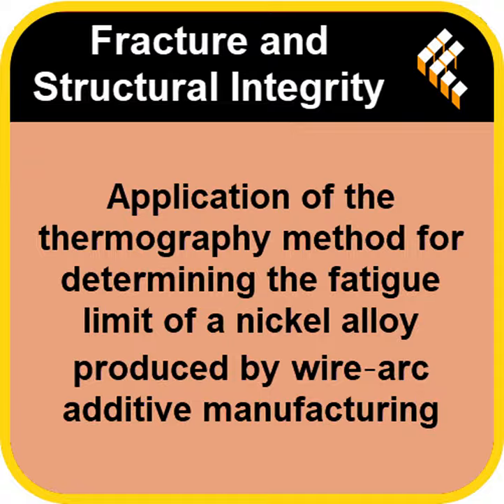So let's get to the bottom line. What does this all mean? We have this rapid, precise answer, 383 MPa. How did that compare to the old, slow, traditional method? Right, this is the validation step, the most important part. They didn't just stop there. They also ran the full traditional SN curve tests on identical specimens from the same batch of Inconel, pushing them all the way out to 10 million cycles.